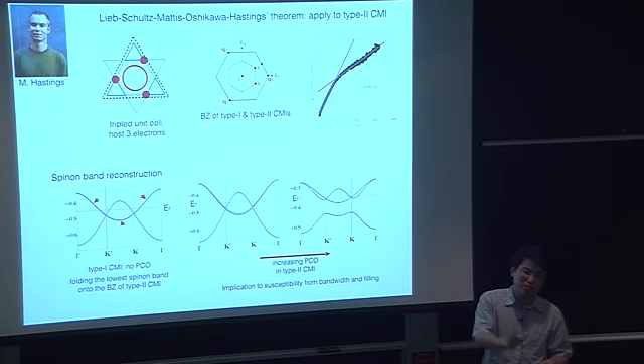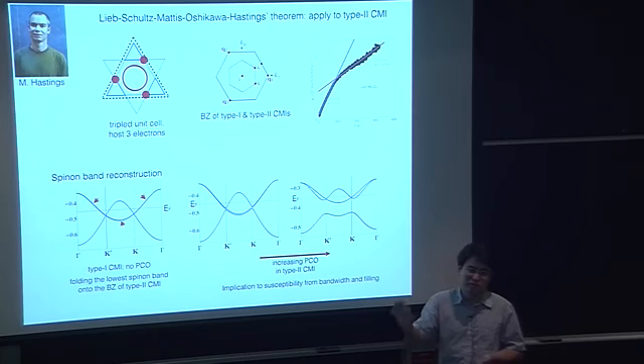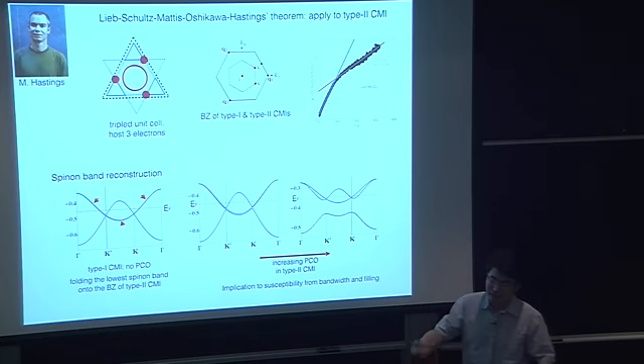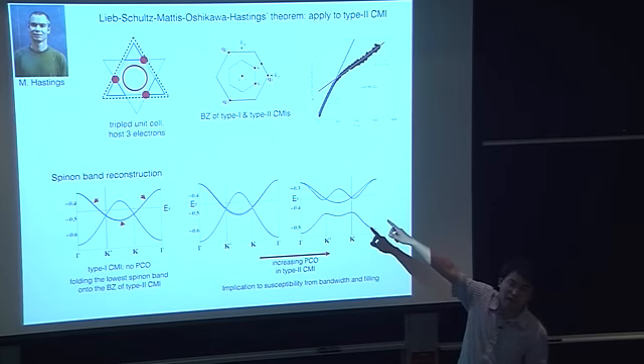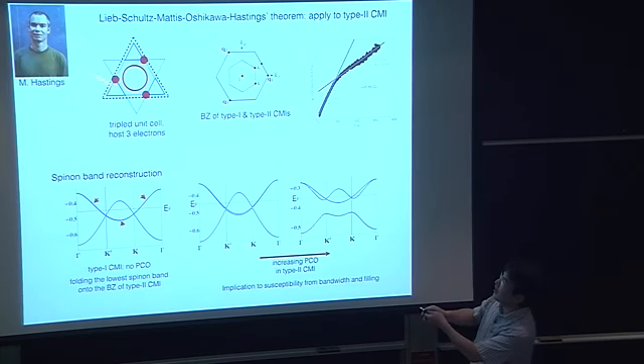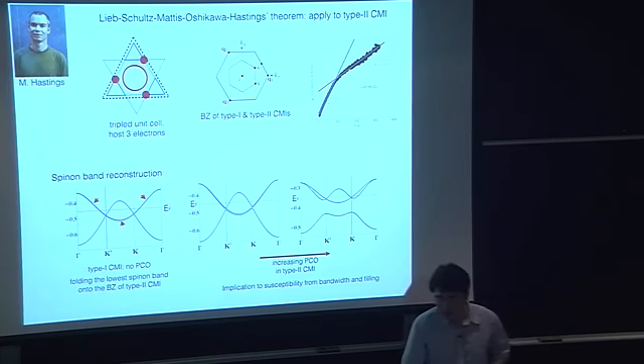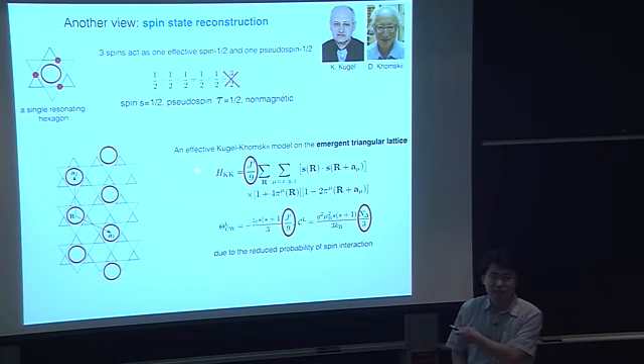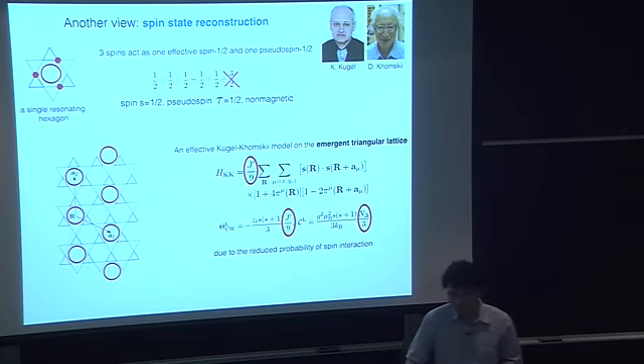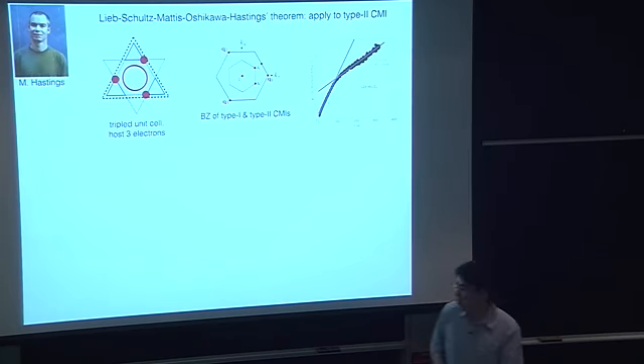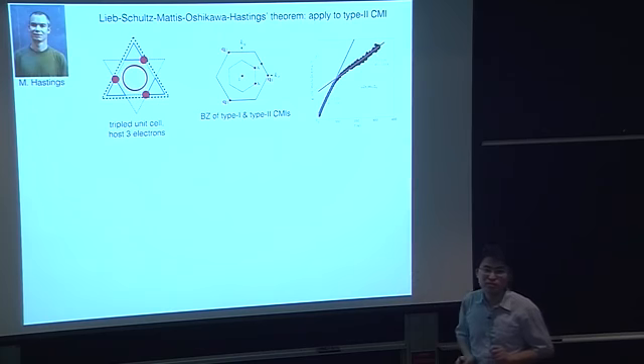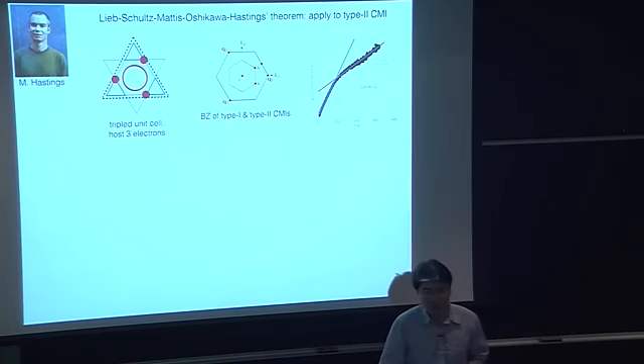I think the misunderstanding is that in the usual triangular lattice case, in the intermediate regime we should use the Hubbard model. In the strong coupling regime, we should use the Heisenberg model, the local moment description. So here, if the electrons are strongly localized inside this hexagon, then we'd better use the local moment point of view, the spin state reconstruction point of view. But if the electrons are not that strongly localized, in an intermediate regime, then we'd better use a spinon band structure picture.